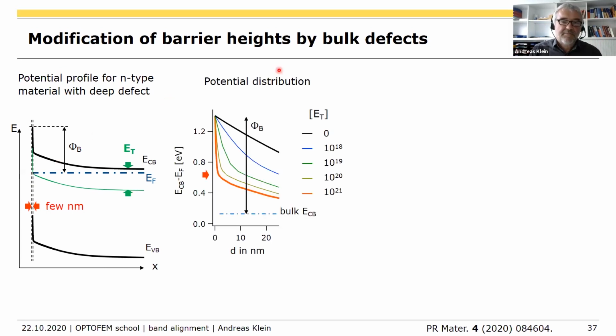So you can calculate the potential distribution, and that's 10 to the 20. That's a reasonable doping concentration for an oxide material or defect concentration. And then you see that this narrow region is just 1 or 2 nanometers. And that means the information depth of the XPS is then not surface sensitive enough to measure the Fermi level here. You will measure somehow an average of the Fermi level.